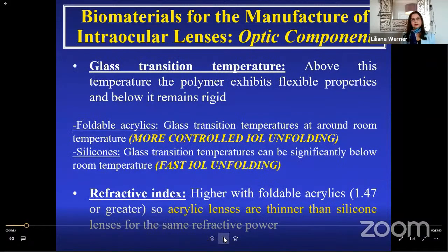These two properties can differentiate acrylic materials from silicone materials: the glass transition temperature and the refractive index. Above the glass transition temperature, the polymer exhibits flexible properties, and below this temperature, it remains rigid. Acrylic lenses usually have glass transition temperatures that are close to room temperature, and therefore they unfold slowly in a more controlled manner. This temperature can be considerably lower than the room temperature for silicone lenses, and therefore silicone lenses show a faster unfolding. The refractive index is usually higher with acrylic lenses, so these lenses are usually thinner than silicone lenses for the same refractive power.